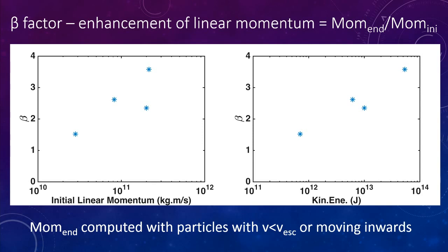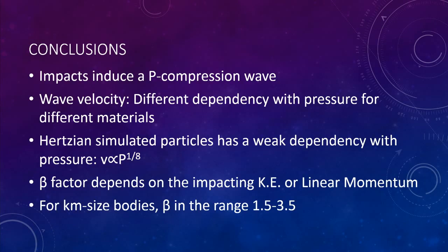The linear momentum is computed with particles with velocities less than the escape velocities, or particles that are moving inwards into the interior of the objects. So the conclusions are that impacts induced a P-compression wave into the interior. The wave velocity has a dependency with the pressure, but also a dependency, as far as we have seen in our laboratory experiment, with the material.